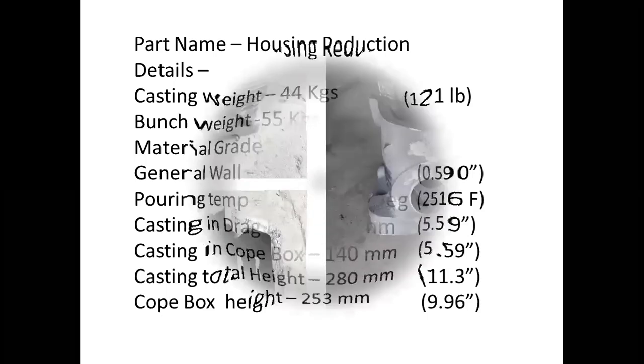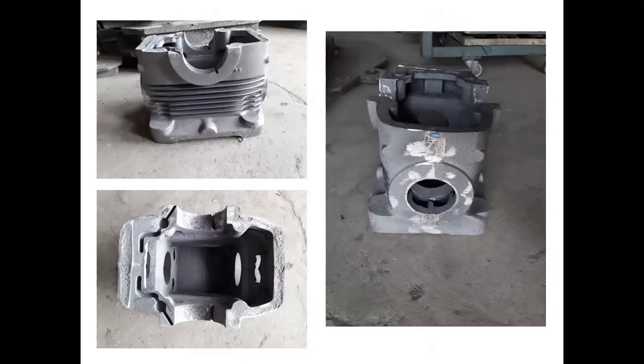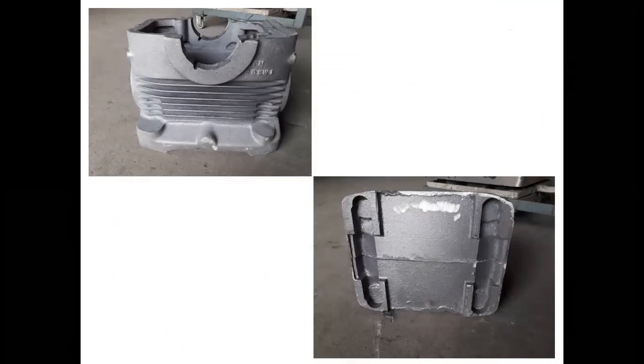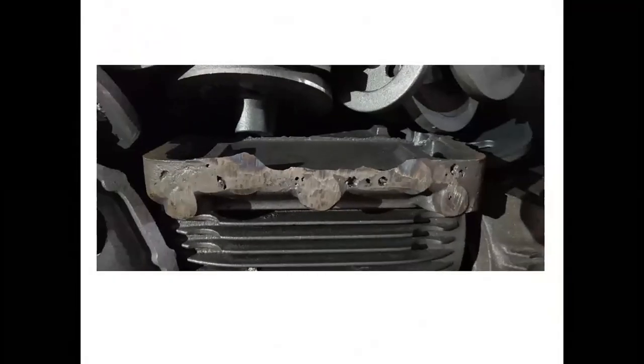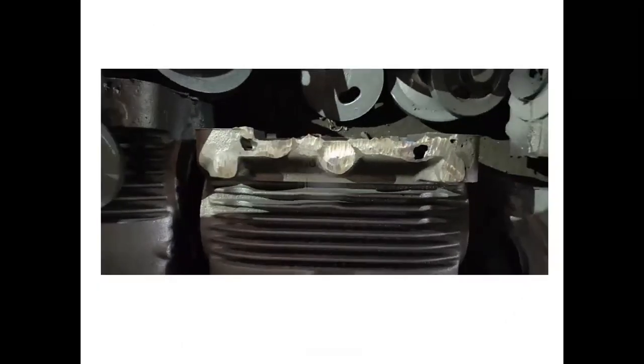Next. This is the casting. In the next slide, the defect photograph is there. All the sides have been shown, because fins are also there. That's why a minimum temperature of 1380 is selected. General wall is more, but the fins are there. Fins are most important. It is a reduction gearbox housing casting. Now you can see the blowhole at the highest point of the casting. Around 40% rejection was there. These are the blowhole defects, clear cut.